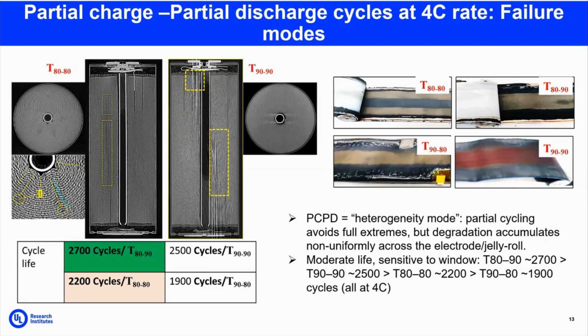near the tab locations, because whatever gas was formed has to escape. So during the escaping process, we can see some deformation near the terminal sites. But if you look, interestingly, the anode aging behavior is completely different for all four test conditions.